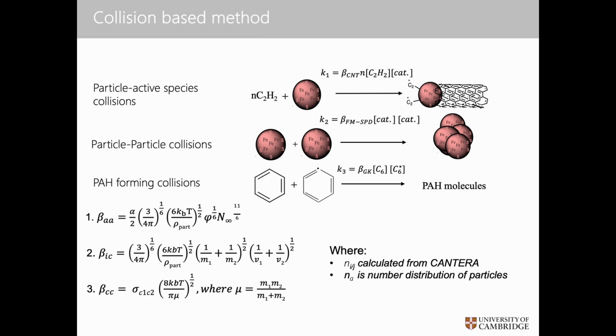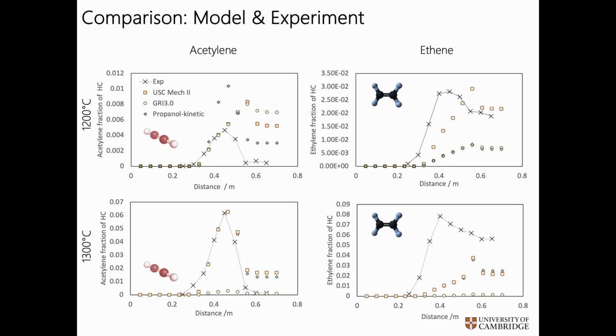We can also describe particle nucleation and growth very well, so we've got some of the tools at our disposal to be able to do this. Just to represent that, the X's here are our measurement data where we're sucking the products out at various points along the axis, so the distance down the reactor, and we can see, for example, how much acetylene and ethene are being produced relative to the models. There's a variety of different models, but by and large, this is a linear scale, not a logarithmic scale. I'm really happy with the agreement here. So we're not far off in terms of being able to describe the carbon chemistry well.